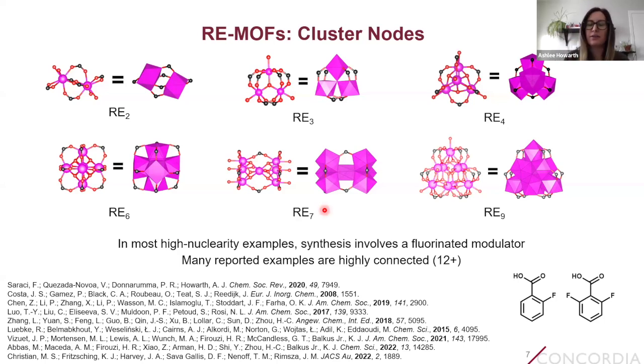And so if you look into the literature at examples of MOFs that have these cluster building units, especially the high nuclearity ones like the hexa, hepta, and nonanuclear clusters shown here, you'll see that the synthesis most often involves a fluorinated modulator, something like 2-fluorobenzoic acid or 2,6-difluorobenzoic acid. And it was originally thought that these fluorinated modulators were required because the fluoro groups are hydrophobic, they protect the clusters from being degraded or hydrolyzed while they're forming.